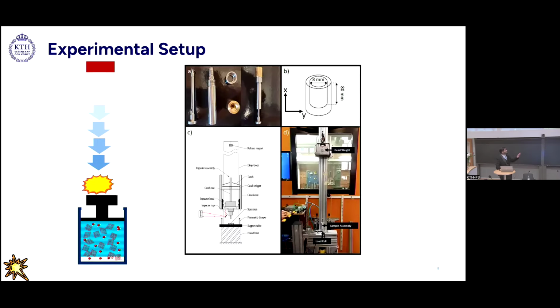So in image A, you can see the experimental chamber, which is roughly 8 centimeters long and 8 millimeters in diameter. And in image C, you can see there is an electromagnet on the top, which holds the weight at the desired height. Upon electronically triggering the signal from the computer, we can drop it on top of the experimental chamber, which will be kept here. Now there is also a laser pointer system, which is monitoring the motion of the drop weight at every time step. And also there is a load cell at the bottom, which is recording the pressure versus time data at every step of the way.